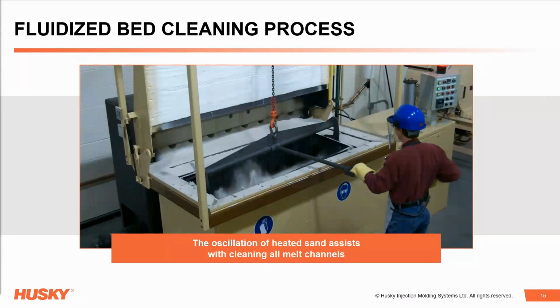The manifold and melt components are removed from the hot runner and immersed for several hours. This is an extremely effective and efficient way to remove resin from a manifold. It doesn't require torches, hammers, or chisels. It also eliminates the need to remove plugs or to drill out melt channels, because all of the above there can easily damage the hot runner, and that'll drastically hurt its performance once you rehang it.